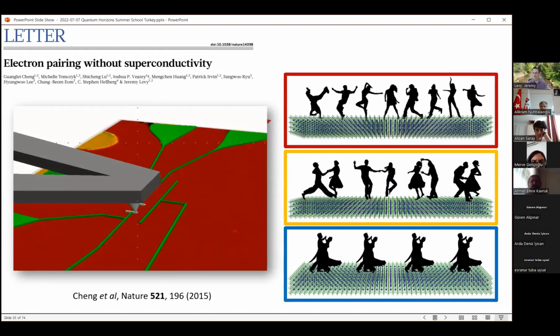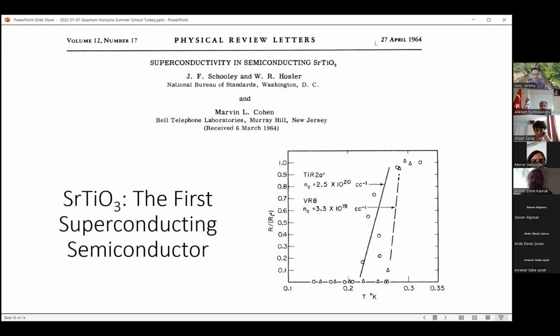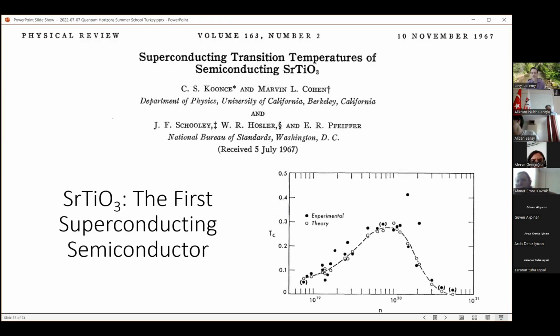So it turns out that one of the many properties of strontium titanate is that it's a superconductor. This is really basically a paper that we published in 2015. But the story really begins in 1964, where the phenomenon of superconductivity in a dilute semiconductor was first discovered. This is a really surprising thing, that you can have so few carriers in a material and yet it becomes superconducting. And in fact, the first superconducting dome was reported in this material. This is 20 years before high temperature cuprate superconductors, which also have this non-monotonic TC versus doping.